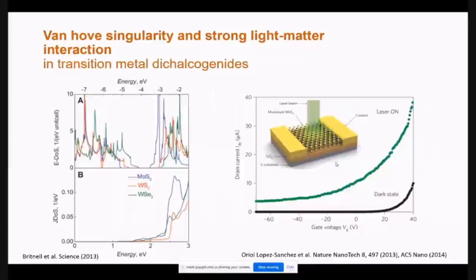The topic of today is, of course, using molybdenum disulfide and its extremely high sensitivity to light. That's another aspect of these transition metal dichalcogenides, in which they have a very strong density of states near the visible range at the edge of the conduction band, and that allows an extremely large scattering cross-section of light by this material. As a result, even a single atomic layer or molecular layer can absorb 6 to 10% of light, which is impossible for usual bulk materials like silicon and so on.